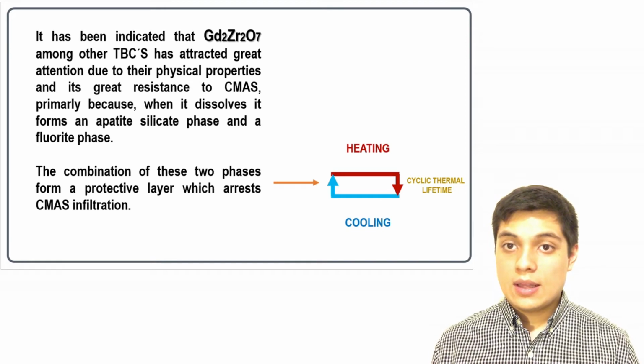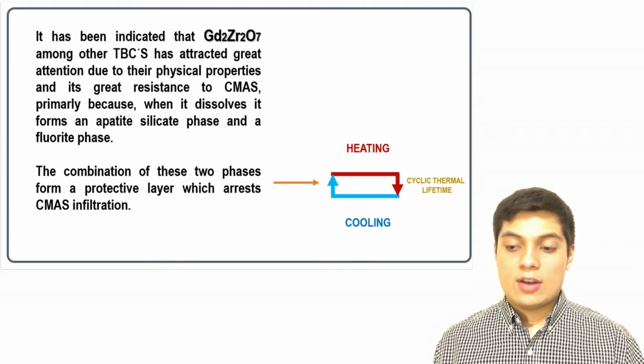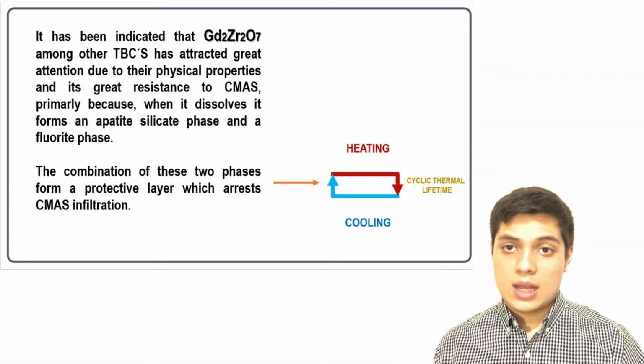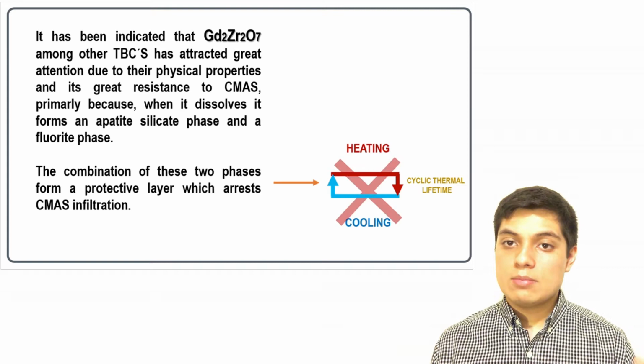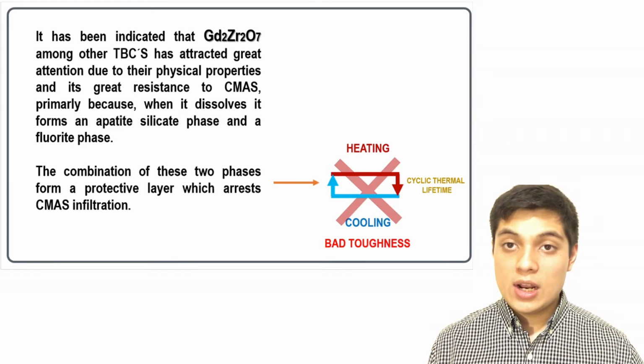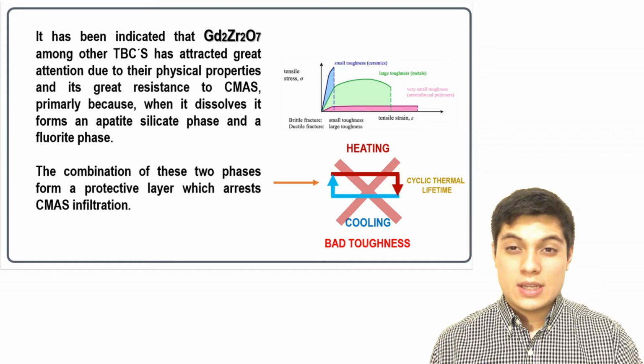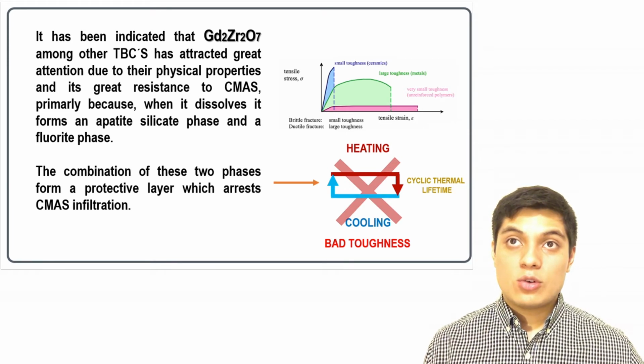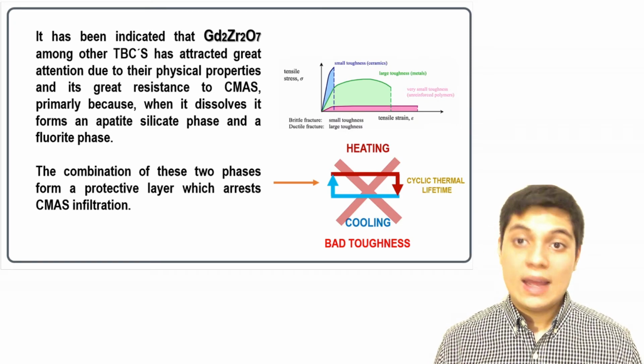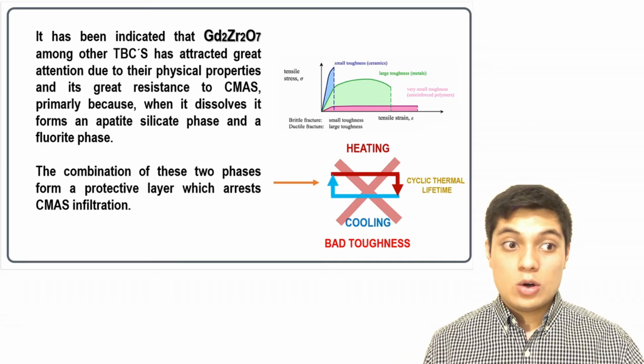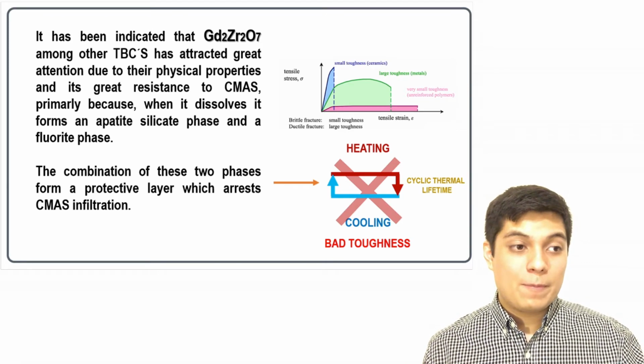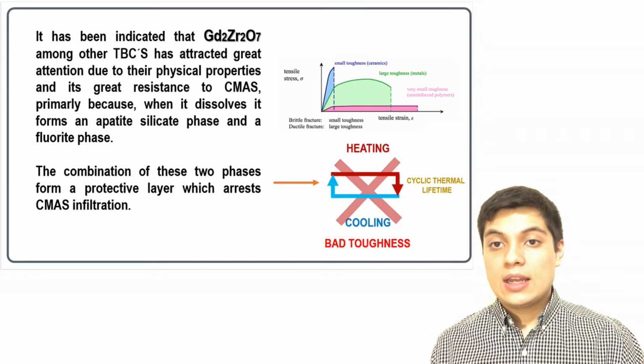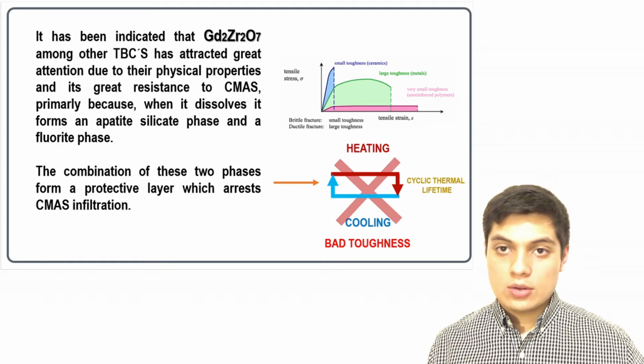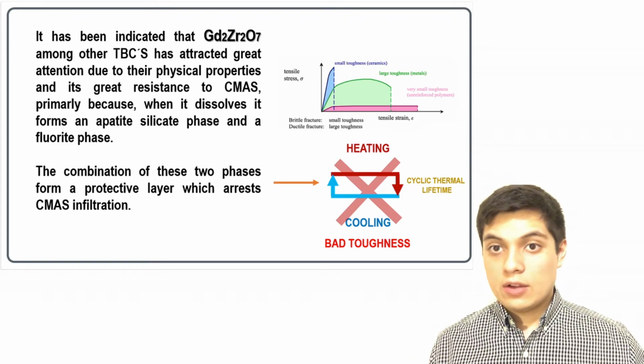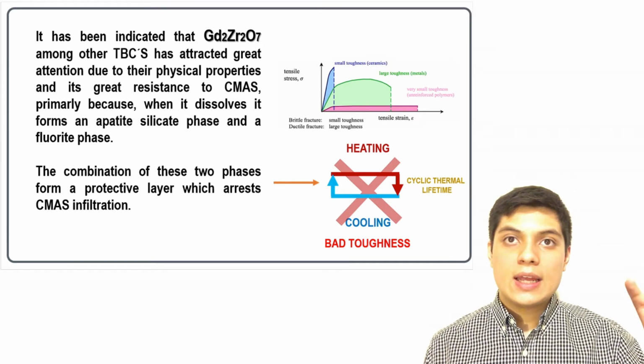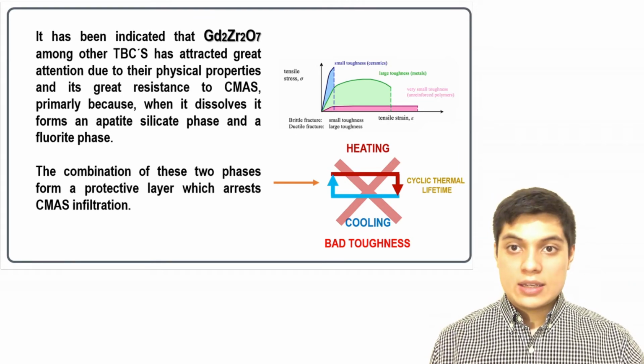But what happens, unfortunately, is that the cyclic thermal life of this gadolinium zirconium oxide is really poor, and this is mainly due to the bad toughness. So when a material has bad toughness, you cannot observe plastic deformation. So when a crack propagates or initiates, it will fracture, and it is harder to predict when this crack is going to occur, compared to materials with higher toughness. You can observe plastic deformation, and you can predict more easily when a crack is going to take place.